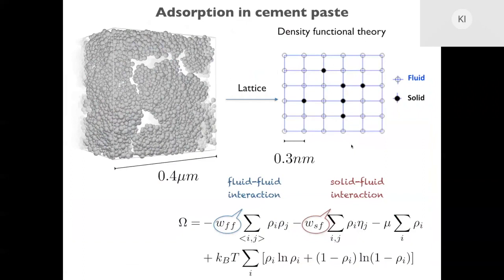And what we did was density functional theory. This is a mean field approach where we write a thermodynamic potential that takes into account the interactions between the fluid-fluid and the solid-fluid. So what is important is to calibrate these two parts, the fluid-fluid and the solid-fluid, from the formations of the materials that we are modeling. So in this case, the fluids we tried were water and nitrogen, because those are the two common fluids people use to probe the pore space of cement. And we also calibrated the solid-fluid interaction from atomistic simulations.